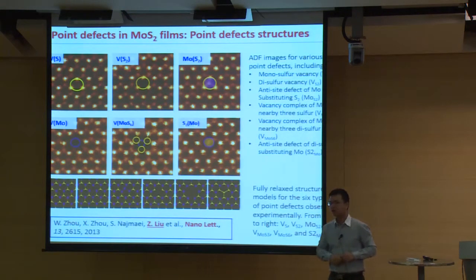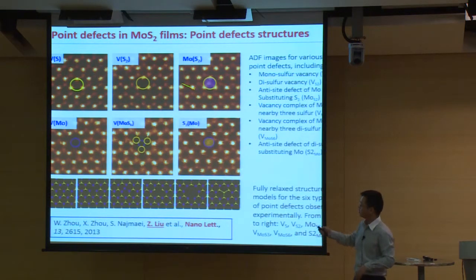Okay, since we can make such high quality and large area devices, we would like to see what exactly it looks like in terms of atomic structures. Okay, so we got some beautiful defects. So we look at the point defects. Because the molybdenum sulfide consists of 3 layers, sulfur, moly, sulfur, the defects vary a lot more than in graphene. So for the point defects, we can get quite a lot, like the 1 sulfur vacancy, 2 sulfur vacancy, and 2 sulfur substituted by a moly. And even more cases, more than 6 types of defect.